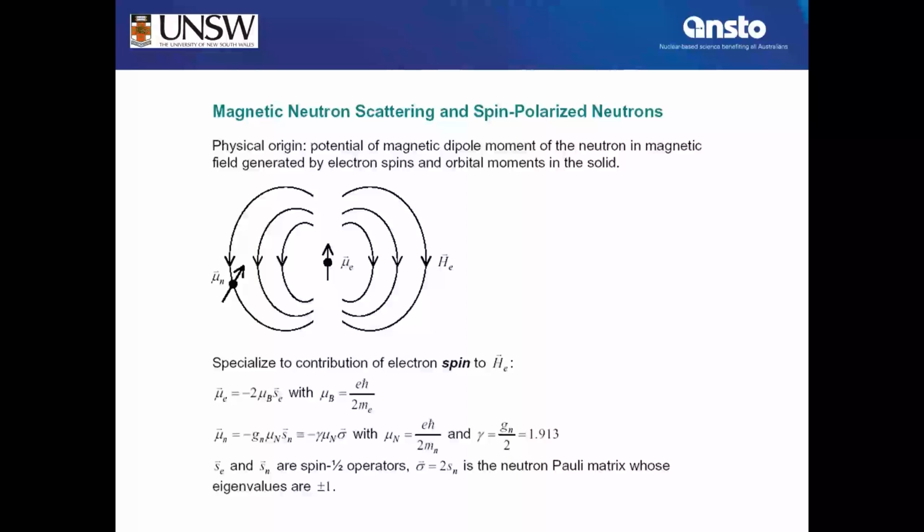And that answers the question why the spins are so important and not the nucleus, not the core, because the mass of the core is a factor 2000 heavier than the electron. So the magnetic moment of the nucleus is a factor of 2000 and more smaller than the electron spin. So scattering at the spins of the electrons, it's always the electrons.